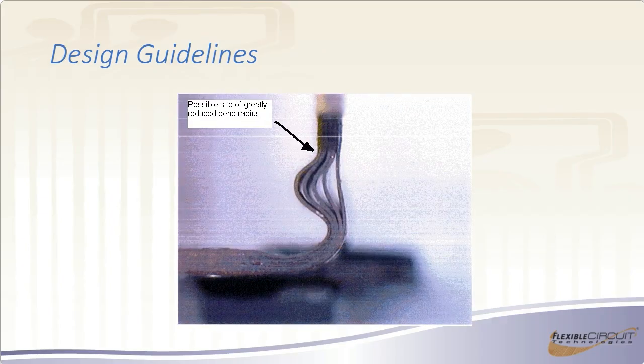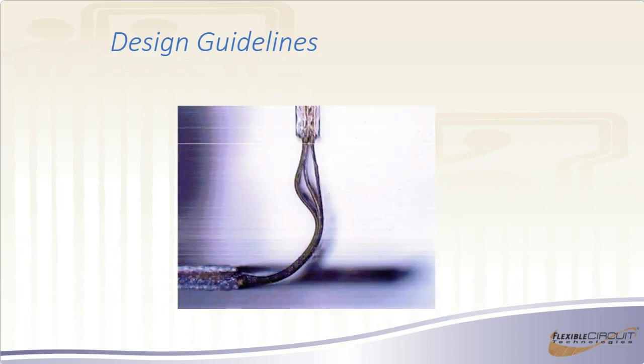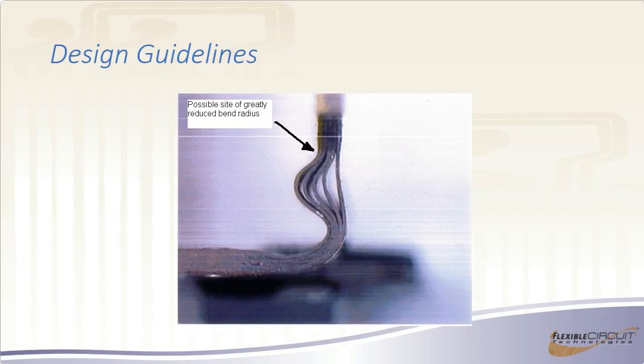And unfortunately, because of the way circuits behave when they're unbonded, we ended up with a secondary reduced bend radius right here, and this was actually bent over 180 degrees when it was installed. So this got even more pronounced than it's shown in this picture here, and they actually got stress cracks in that area. So in this particular application, being just a little bit stiffer was acceptable, and that's where they probably should have stayed. Going with more flexible actually caused more problems. So there is a balancing act there. And again, that's one of those things that we learn as a manufacturer, and so it's a good idea to give us a call so you can lean on our experience.